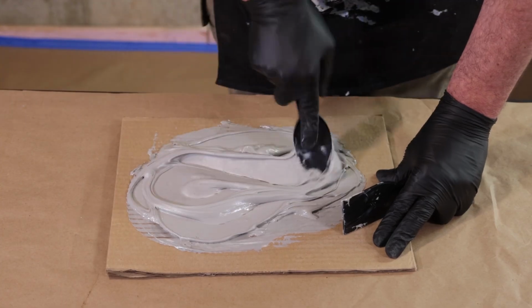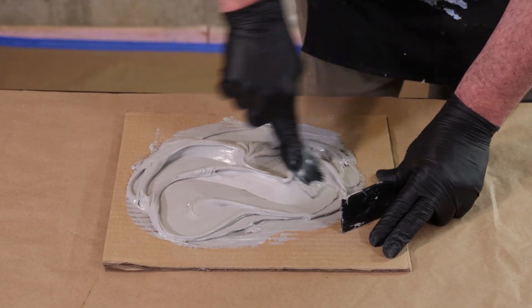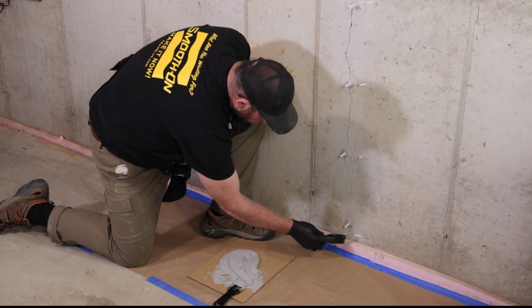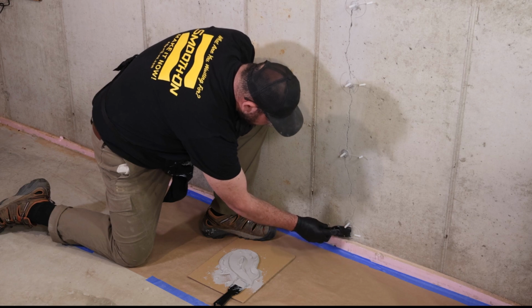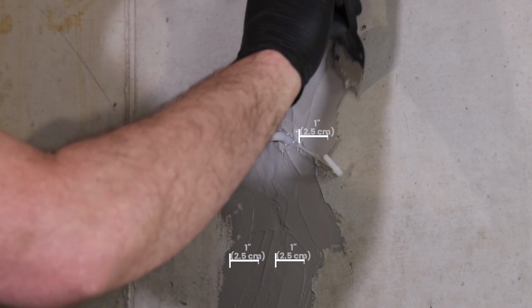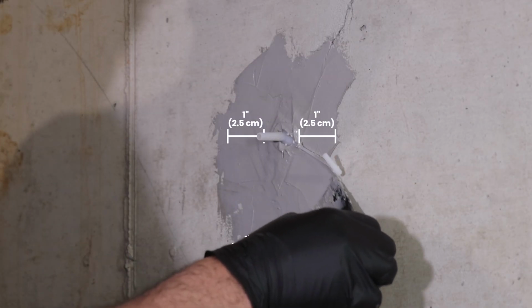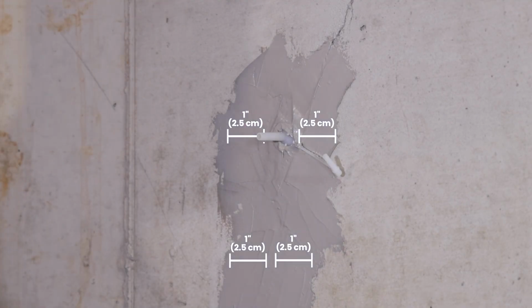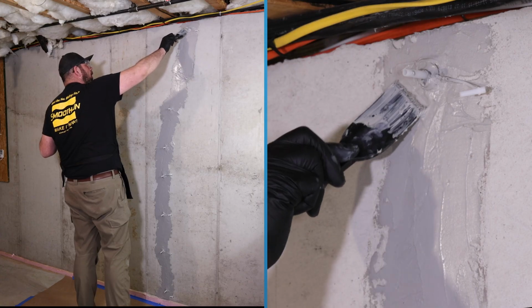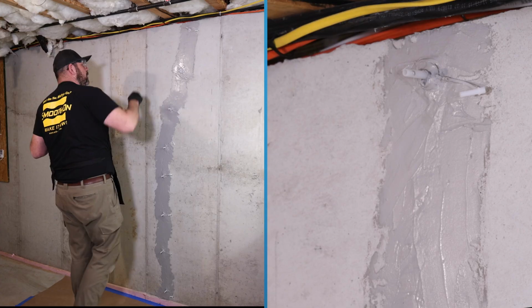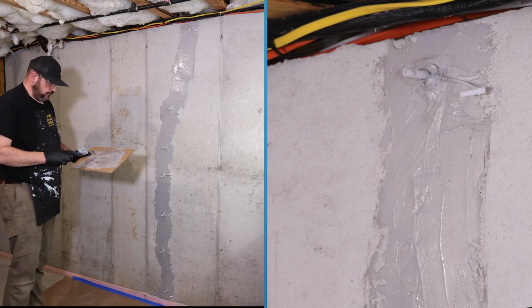Once the ports are secured, mix enough paste to cover the crack. Apply at a thickness of about 1/8 of an inch, fully covering the edges of each port and extending at least 1 inch beyond both sides of the crack and around each port. Allow this paste to cure for at least 16 hours at 73 degrees Fahrenheit before continuing.